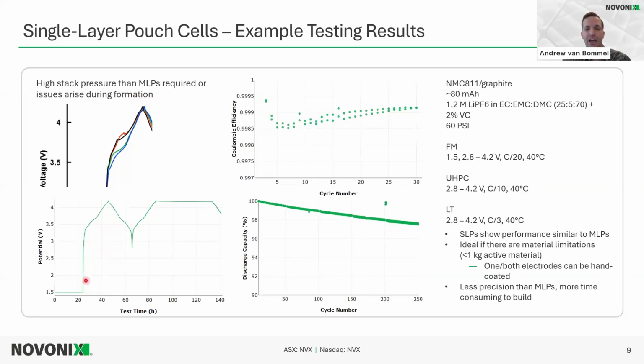So this formation graph here was done at 60 psi stack pressure. So our standard formation is a hold at 1.5 volts. This is the wetting step for 24 hours. And then all these are C/20, so a charge to the upper cutoff voltage for 811, this would be 4.2 volts. Discharge and then charge back to 4.2 volts. And then there's an open circuit step that we use to see that relaxation current. It can show the quality of the cell and if there's any soft shorts in it as well. And then a discharge to a safe voltage prior to degas.